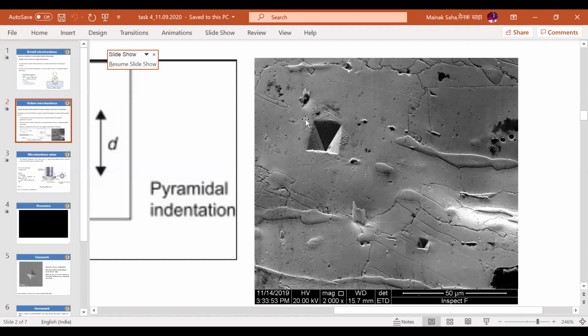Here you can see one orientation, a northeast type of lines, and here a northwest type of orientation. So what is happening is that two slip systems are activated at the same time. Plastic deformation occurs by the activation of two slip systems.